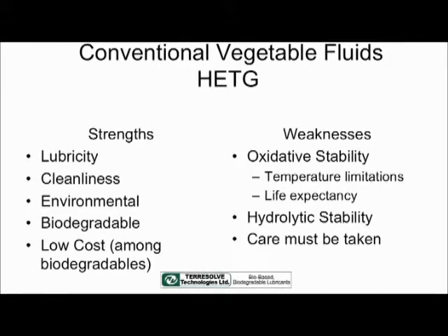Also, a little bit of water in the system will cause them to hydrolyze and break down and form acids and create wear. So if you're going to be using a conventional vegetable oil HETG type of product, you have to expect relatively short change-out intervals. You must take care that the system operates at a relatively cool operating temperature and that you keep that clean and dry. Not that hard to do in many applications, but in some applications it's virtually impossible.